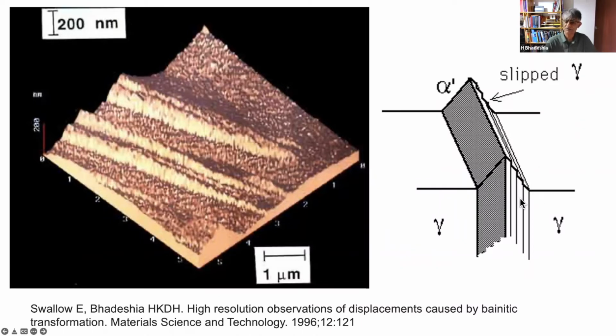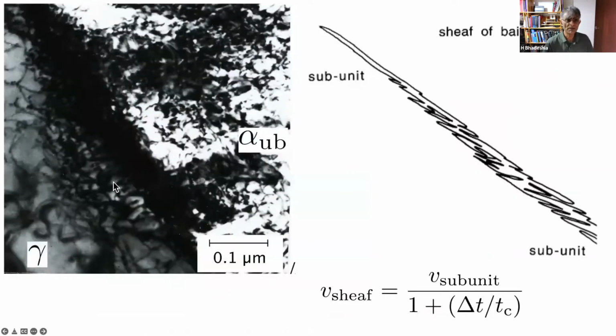But there is a consequence of this shape deformation, is that if I look at a transmission electron microscope image of this interface here, you see masses of dislocation tangles both in the austenite and in the ferrite. Now, a displacive transformation requires an interface which can move in a glissile manner. That means glide like ordinary dislocations without interference. If you put obstacles in its way, then it will not move, just like dislocations will not move when you precipitation harden the material. So what happens is that as these subunits grow, you are accumulating dislocation debris at the interface, and once that is large enough, this actually stops.